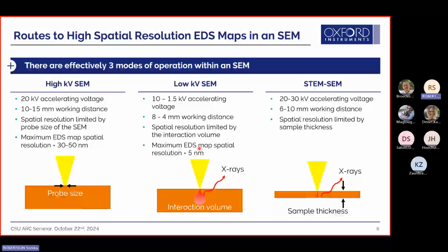The STEM mode in an SEM, we're not doing 200 kV, what we would do in a TEM. In an SEM, you can, though, go up to 30 kV, and your working distance, again, 6 to 10 millimeters, and this time your spatial resolution is limited by the sample thickness, because when you're doing transmission mode in an SEM, you're still trying to get an electron transparent sample.